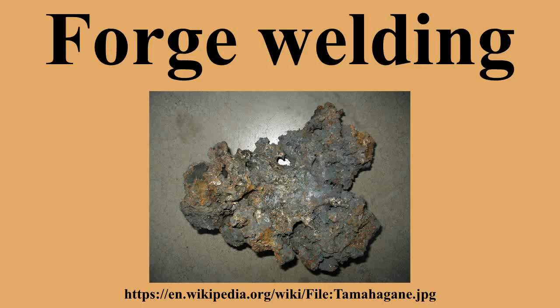The steel may take on a glossy or wet appearance at the welding temperature. Care must be taken to avoid overheating the metal to the point that it gives off sparks from rapid oxidation, or else the weld will be poor and brittle.